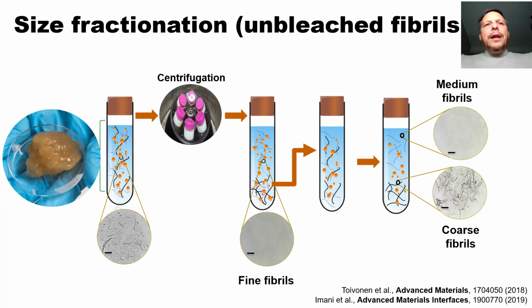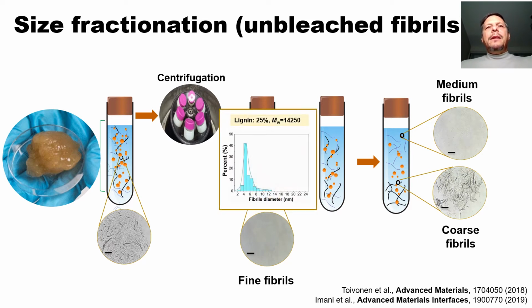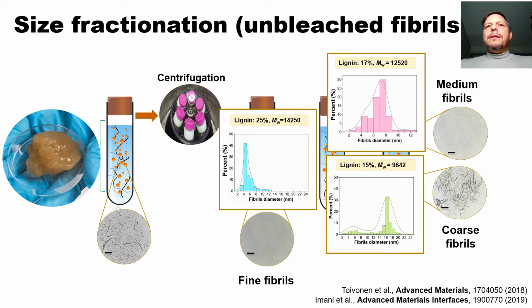Now, if we turn our attention to the case of lignin-containing fibrils, I think we can pretty much arrive at similar conclusions. So here we're looking at size fractionation, the same way that I explained for lignin-free fibers, but in this particular case with high yield fibers. And we go from very fine fibrils that come from the same fiber source, but just by the fact that we're doing fractionation, we find that the amount of lignin in those finer fibrils is actually higher than those that are of medium size or the coarser ones. So there is a relationship between lignin concentration and fibril size when we take a population of fibers that are processed by the same unit, by the same source material, just that we fractionate in sizes. So there is a correspondence between fibril size and lignin content, as well as the molecular weight of the lignin.